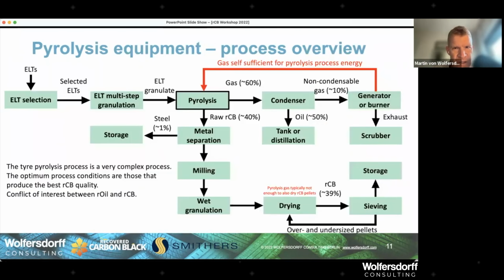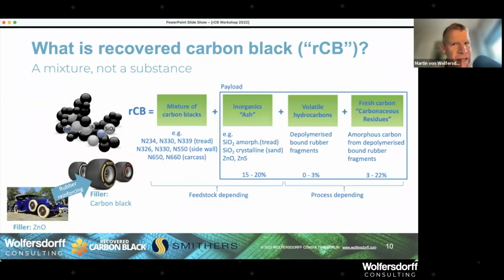The other question from Ignacio was about the types of undesired silica. Now, you could argue silica as a whole is undesired for sure in Europe, because if you want to get below 20% ash, then we could argue for the short term with the sameness approach under REACH that we have a carbon black, not a recovered carbon black. There is a type of carbon black that is allowed to have 20% ash. And if we fulfill that, and that's not the only condition we have to fulfill to have the sameness approach with carbon black, there are other items we need to cover as well. But the general ash level needs to be considered.